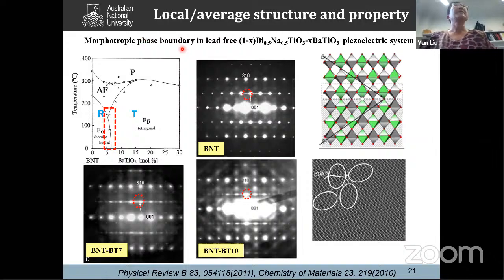This is bismuth sodium titanate, barium titanate, a typical lead-free piezoelectric material. In this morphotropic phase boundary, there is a phase transition from ferroelectric rhombohedral to ferroelectric tetragonal, and we can get the optimal piezoelectric performance. A lot of people are working on this and trying to understand why this excellent piezoelectric property is only observed in this phase boundary region.